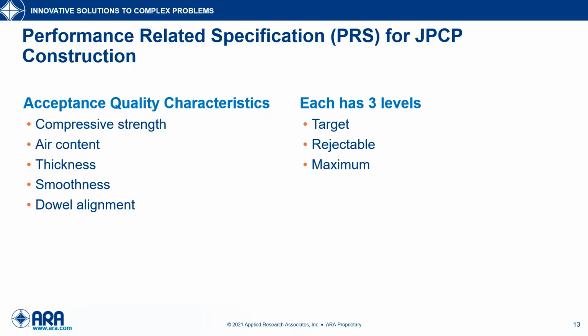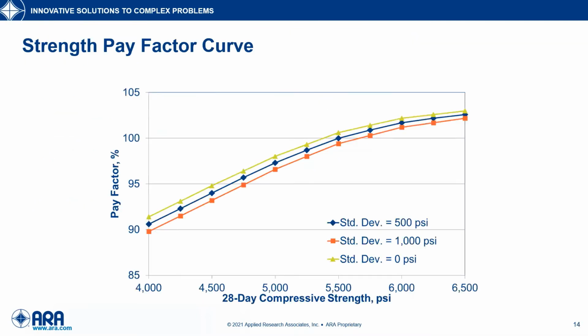And I'll show a couple examples of the strength and thickness pay factor curves coming up here. So this is a plot of the strength pay factor. These curves are calculated using life cycle cost assessment. And for strength, higher quality here is defined by increasing strength. The multiple lines are for different standard deviations of the data, and similarly there, higher quality is defined by decreasing variability through the standard deviation. So these values were included in the specification and are unique to the 13-inch jointed pavement that we built on the I-90 corridor.